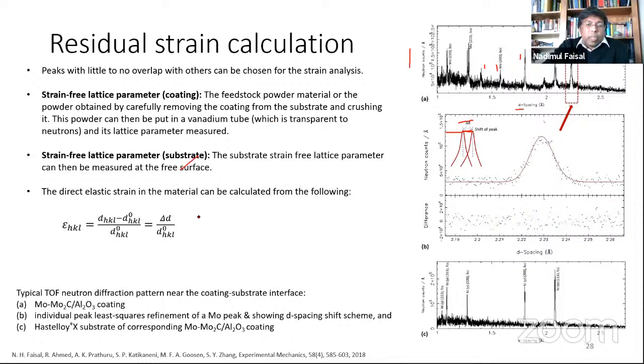So in this equation you can see here, d_hkl and d naught. d naught is a strain-free sample. So d naught is important here. Based on d naught, you will know what your strain is. If your selection of the d naught is not properly thought about, then you may get very high or very low strain. So what we did in our experiments, in different experiments, we took the coating off from the substrate and crushed it into powder form. That is one way. Or you can use the feedstock powder itself, before you spray it, as your sample for d naught measurement.